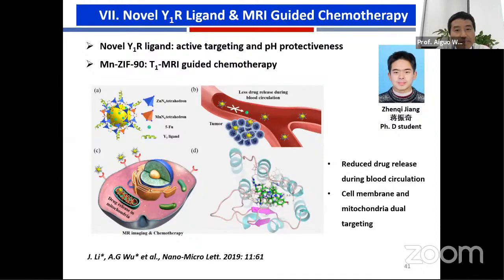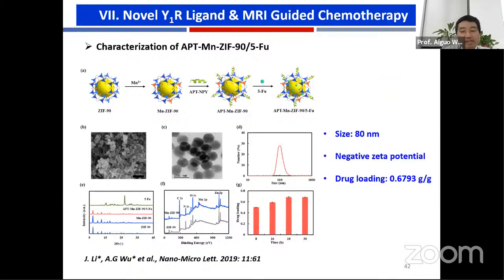And another case I want to show you is we want to use the Y1 receptor ligand to get, for example, some imaging guided chemotherapy there. So here we resort to a system, Mn-ZIF-90. Here we use manganese ions to exchange the zinc inside the ZIF-90 to get the T1-MRI signal. And this can let the T1-MRI guide the chemotherapy there. Because this system can reduce the drug release during the blood circulation and also has cell membrane and mitochondrial dual targeting there. And we found the size of the nanosystem here is 80 nanometers, with a negative zeta potential and a very high drug loading rate there.